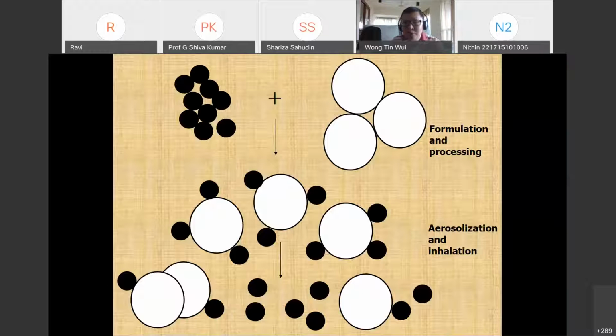Right? So this system appears to be ideal for simple reasons. Upon aerosolization and inhalation, the particles can actually reach the deep and peripheral lung due to their small size. And in the deep and peripheral lung, the nanoparticle can detach from the micro scale particles and act on the cancer cells, for example. And even if the nanoparticle is not detaching, at least the whole assembly of the particle will reach the deep and peripheral lung, right?